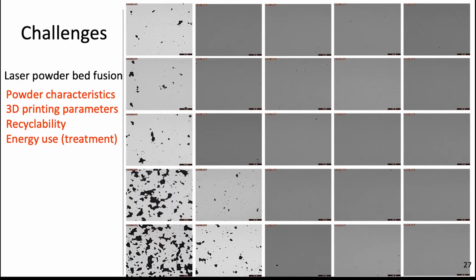So there are challenges, there's no fairy tale, there are always compromises. The 3D printing of alloys can produce these horrendous pores, the scale marker here is not clear, but it's about 0.5 millimeter. But if I change the 3D printing parameters, I can avoid those pores. So one way to foster this technology is to develop new materials that are resistant to pore formation.